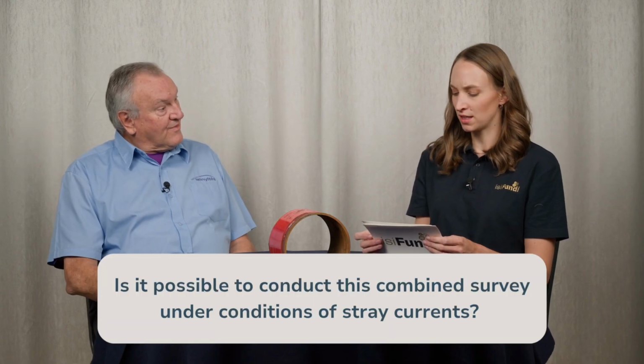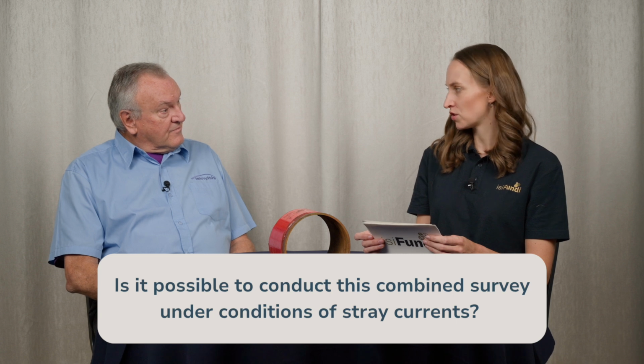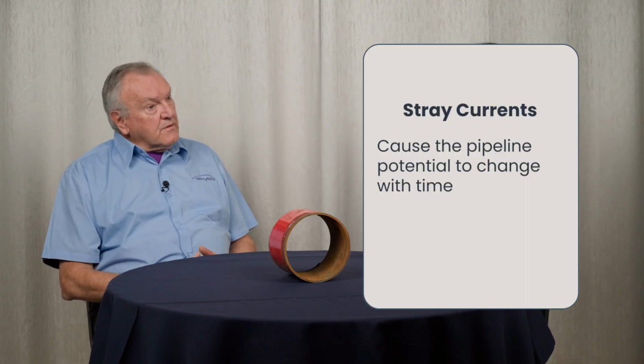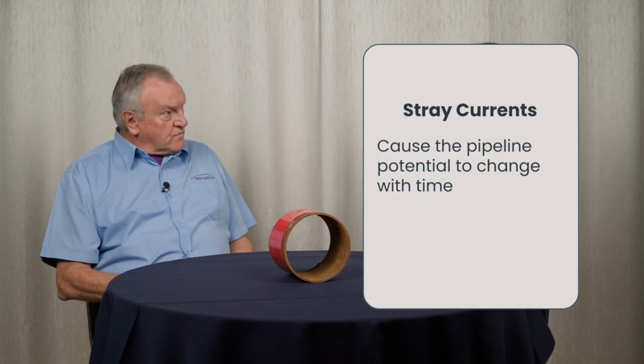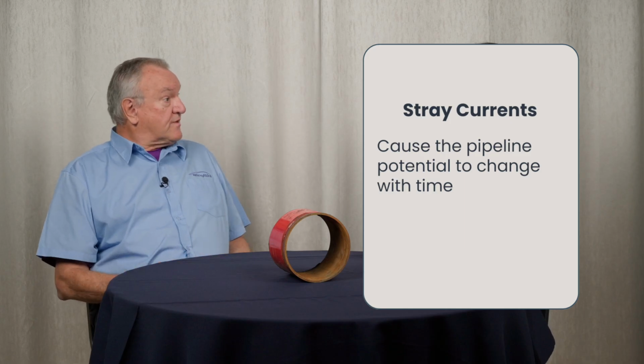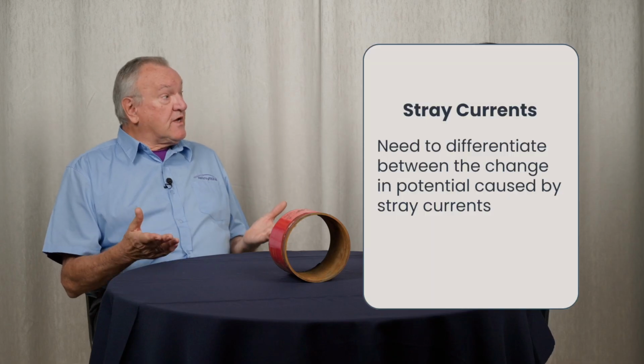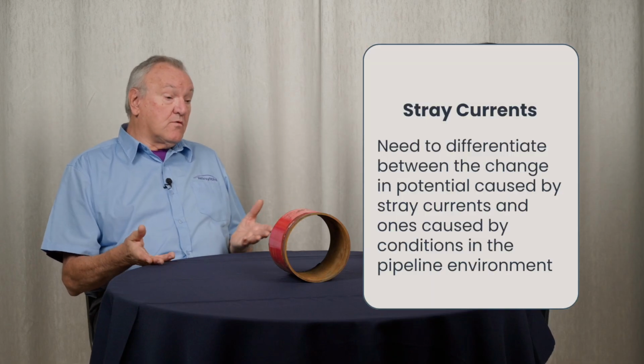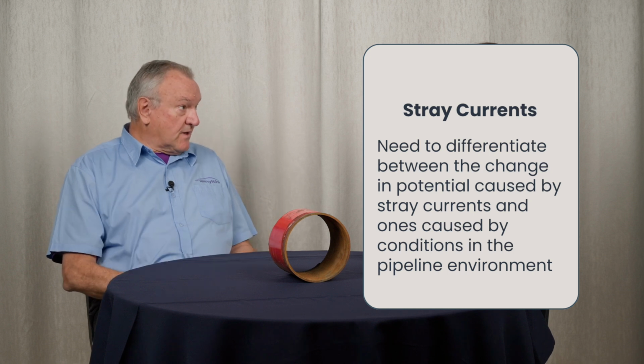Now, is it possible to conduct this combined survey under conditions of stray currents? Yes, it is. And that's actually one of the hidden benefits of this combined survey. A lot of standards and operators have the misconception that you should not do CIPS surveys under stray current conditions because the stray current conditions actually cause the pipeline potential to change with time. You're measuring pipeline potential. So now you've got to differentiate between a change caused by stray currents and one caused by conditions in the pipeline environment.